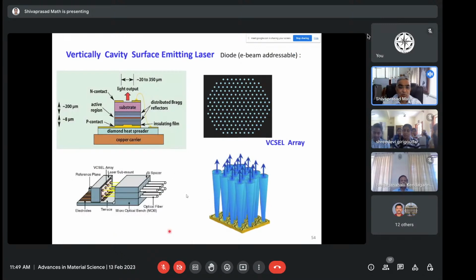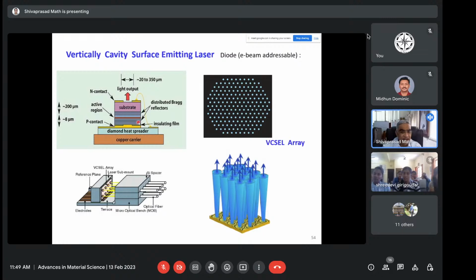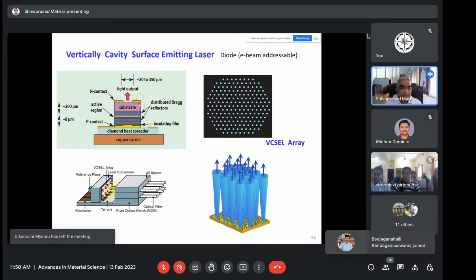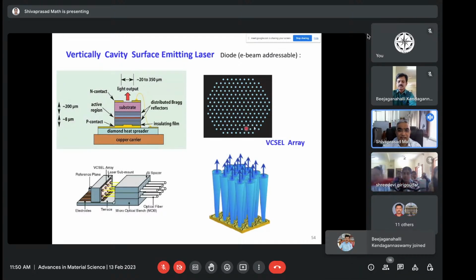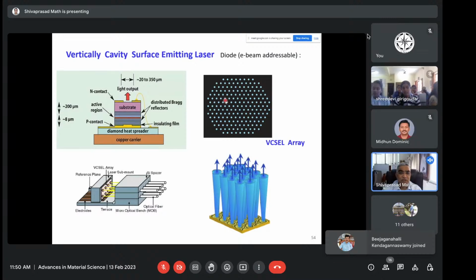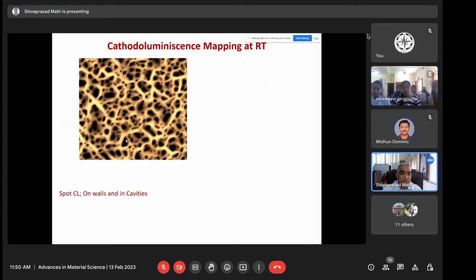Now, as I told you, to put that 1553 nanometers laser, I need to create many lasers coupled to each other, with the light coming out in a very sharp way so that I can put it into the fiber optics. So the lasers are made like this, a very complex structure. You see multiple layers of different materials, Bragg reflectors, many active regions, substrate, and so on. We thought we already have a material like this, so let's see how the light comes out of it. We took this material, which looked like this from the top. It's a lot of pores, which are just formed by kinetics.